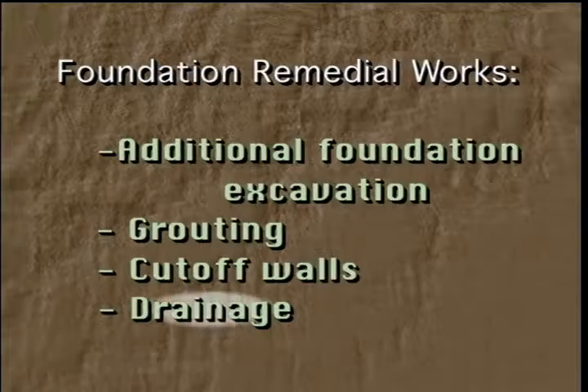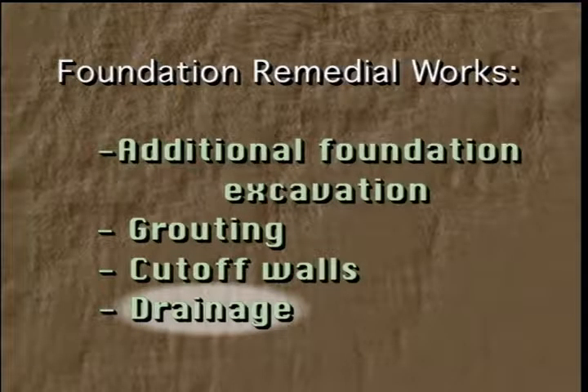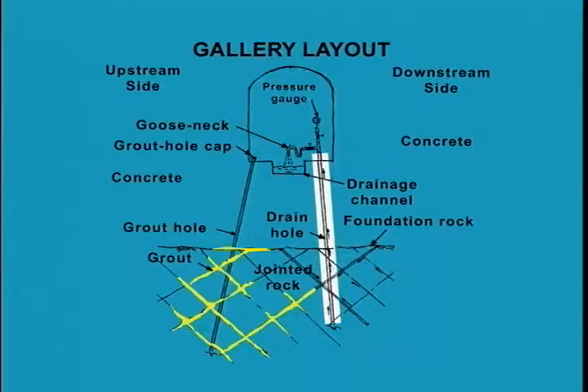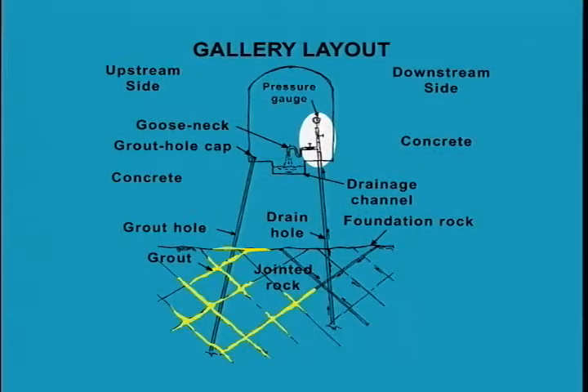Drainage control in the foundation is essential for dams. Concrete dams customarily have one or more grouting galleries close to the rock foundation for grouting the rock, with grout holes drilled from the upstream part of the gallery floor angled 10 to 15 degrees upstream. The gallery also serves as a drainage gallery, with drain holes drilled from the downstream part of the floor angled 5 to 10 degrees downstream. Drain holes may be from 3 to 4 inches in diameter, spaced at 10 to 25 foot distances, with lengths similar to or somewhat shorter than the grout holes.